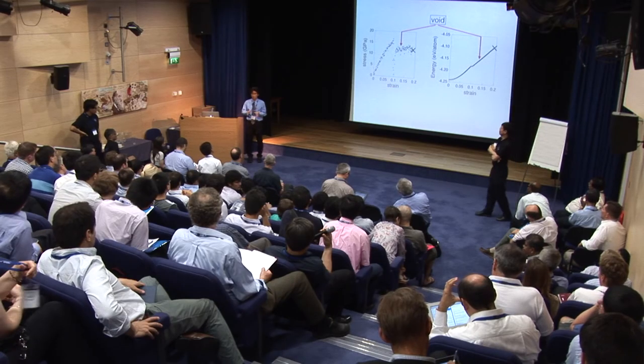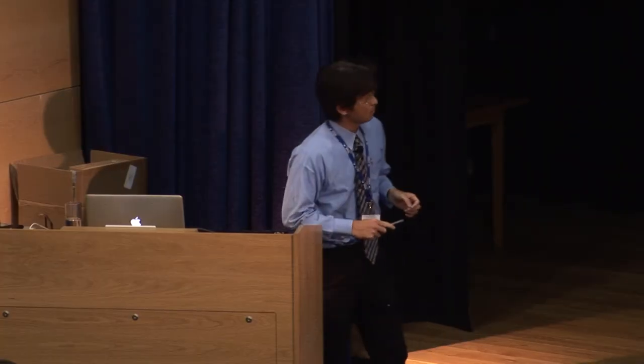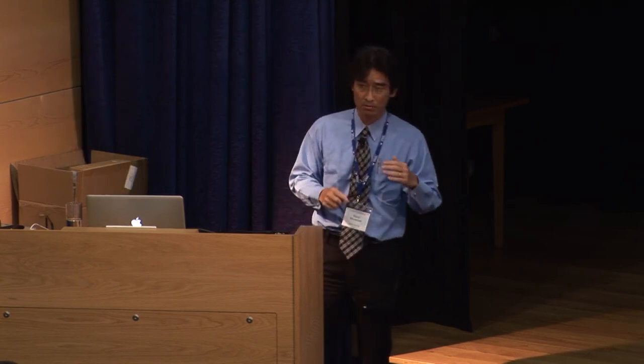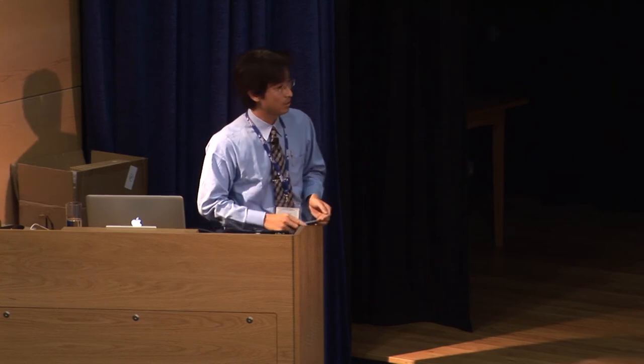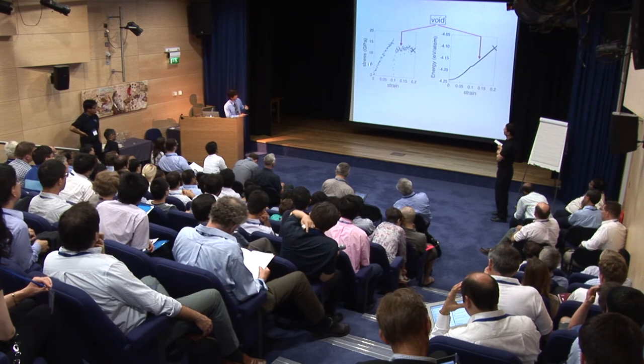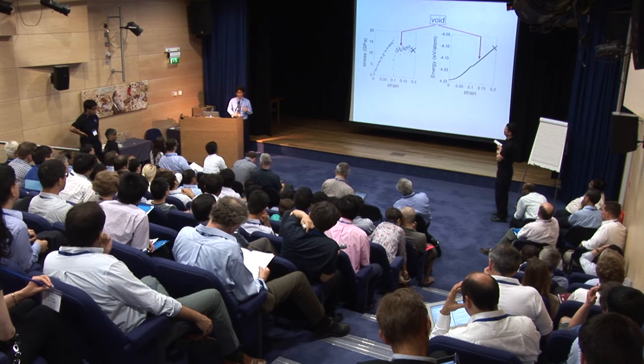My simulation is a very small size, and there is no dislocation source. So if the MD cell induced the dislocations, they quickly remove the stress, the atomic force. So the stress goes quickly down, but the work hardening is working in this area, so the stress goes quickly up. Okay, all right, thanks.